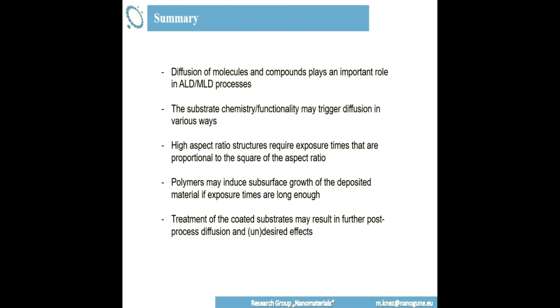The treatment of coated substrates is also a very, very important point here. Don't forget that with the ALD coating, the story is not ended. Your coating may change also afterwards. It's not a static system. Some of the coatings even just decompose in the air, so you need also to be aware of that.